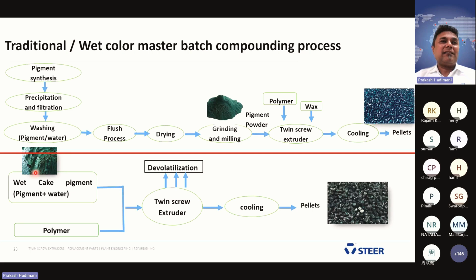In the wet pigment route, we use the wet pigment straight away, along with the 60% water. We take the polymer, pre-blended, and use a side feeding mechanism to push it into the twin screw extruder. Once inside the twin screw, we do devolatilization, meaning dewatering, in three locations to remove all the 60% of water. Once this is done, dispersion is done in the same stage. After that, same as the traditional method, quenching, strand cooling and then pelletizing.